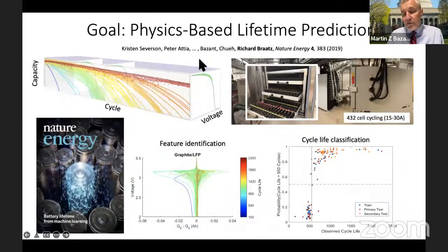And now to connect this back to a theme I think you'll be hearing about in this seminar, the symposium, we in our group in this D3BAT Center, now led, and I say we, but mainly led by my colleague Richard Braatz, have been using machine learning methods directly on battery data for current and voltage to optimize battery use and predict battery lifetime. And in fact, Richard's group showed already a few years ago that simply by observing the first few cycles of a battery, and you apply machine learning methods to correlate with lifetime, we can actually sort the cells into good ones and bad ones and predict with pretty high accuracy which are the good ones, which is a very important breakthrough for industry, because one of the slowest and most costly parts of manufacturing is forming those cells through an early cycling, sort of stabilizing them, and also quality control, deciding which are the good ones, which are the bad ones.